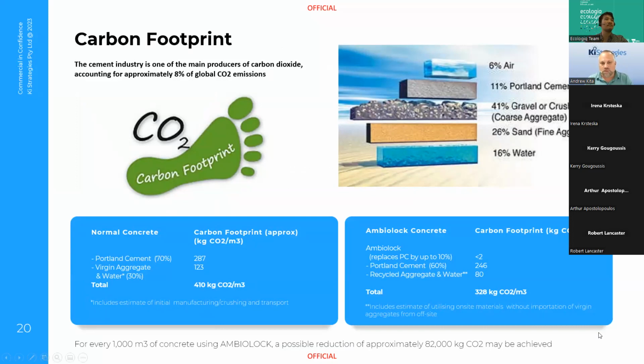So one of the things we've been able to achieve is reducing the carbon footprint associated with using concrete as an encapsulation or stabilizing agent. And we know that the cement industry is one of the largest emitters of CO2 globally. Ambiolock, when used in a concrete or a stabilized sub-base material, is able to significantly reduce the amount of Portland cement required or equivalent binder, and also through the use of recycled aggregates, reduce the footprint even further, as opposed to having to import virgin aggregates from offsite. And we believe that a saving of around 20% in CO2 is achievable, possibly higher with stabilized sand and other materials where cement replacement can be greater. We think for every 1,000 cubic meters of concrete using Ambiolock, the savings, roughly 82 tons or thereabouts, is the estimate. Next slide, please.